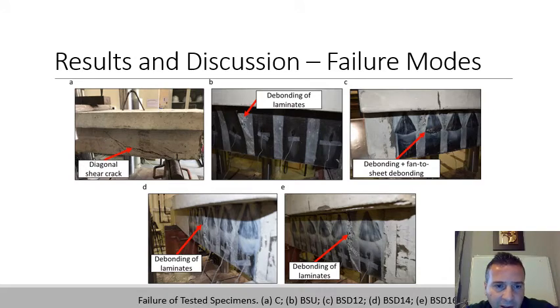You can see here the experimental failure modes. These are the beams at failure. The control beam failed by a conventional diagonal crack at about 45 degrees. The one without anchors fails by debonding, the typical failure mode, debonding of the sheet away from the surface. And here you have some pull out of the flange, so debonding of fan to sheet. Debonding here was prevented and delayed.